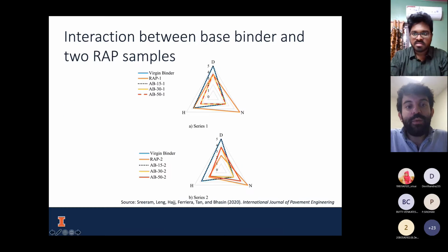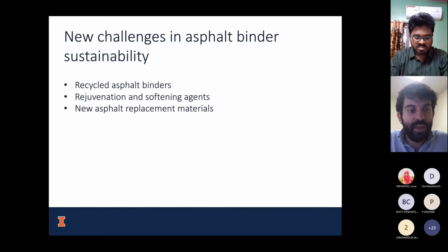Next thing, we want to check the interaction between the base binder and two different wrap samples. So this was also done in this study, right? We checked the dispersive forces present in mixes of wrap and base binder. And again, that's another way to identify which wrap is more prone to recycling and better wrap blends with specific virgin binders. So compatibility is important. I suggest definitely to keep the compatibility in mind as you explore this material.